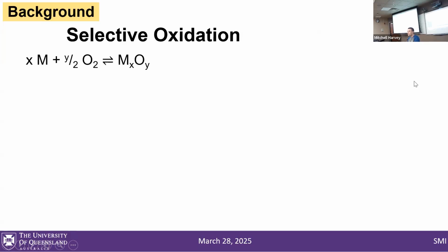Gold, for instance, is very noble. If we have a chunk of gold, we can heat it up in air to very high temperatures, even to its melting point, and then when it cools back down, it'll be just as shiny as when you started to heat it up. Other metals like iron are fairly reactive in air, and if you have an uncoated iron specimen in the right atmosphere, it'll oxidize quite rapidly. And then metals like sodium are extremely reactive and they'll react instantly.